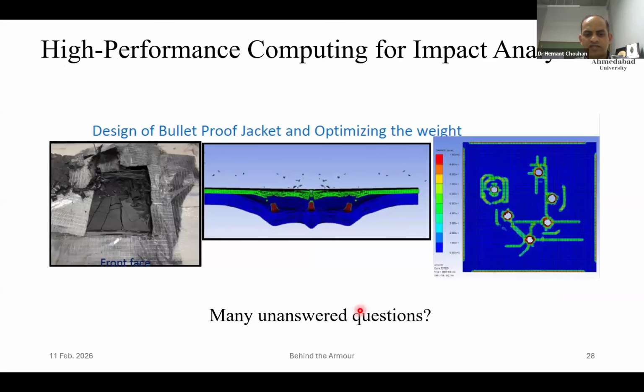But this problem is not that simple, because in the previous slide we have seen that one bullet is handled, but in reality, as per NIJ for AK-47, you are going to fire 6 bullets. In a real test, after one bullet the material gets sufficient time to recover. A bullet is fired, we see the panel, take it, turn around, check whether it is perforated or not, set the system for the next round. In the process, typically 8 to 10 minutes are gone.